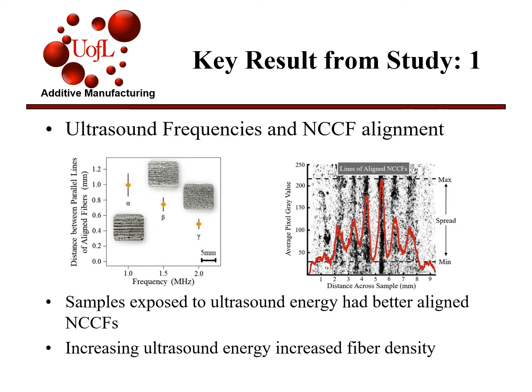The first study from this experiment looked at how introducing the photopolymer resin to ultrasound frequencies during the 3D printing process would affect the alignment of the nickel-coated carbon fibers within the polymer. So the results of this experiment showed that during the process, when they did introduce ultrasound frequency to it, it did improve the alignment of the nickel-coated carbon fibers. And as the frequency of this ultrasound energy increased, it actually increased the density and better aligned the carbon fibers.